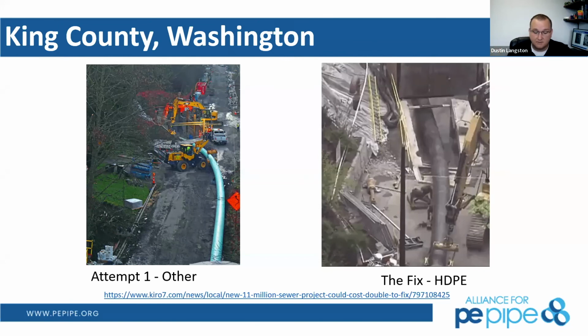The contractor, for some reason, went with fusible PVC the first time, and this was for a drainage system. It was a very, very deep directional drill, by the way, and it was down a hill, and it would collect water into a tank anytime it rained, so that you could treat that water before they released it into the Puget Sound. And the first rainstorm came after the installation, and those tanks did not fill. There was no water. And so because there was no water, they camera inspected the line, and they found that there was catastrophic failure, and the line was completely full of debris.